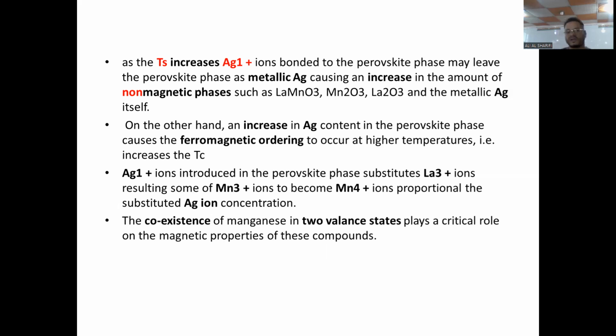Why, when increasing the sintering temperature, does the Curie temperature decrease and get far away from room temperature? Because the silver ions, or doping element ions, here it's silver, bonded to the perovskite phase may leave, may run away from the perovskite phase as metallic silver, causing an increase in the amount of non-magnetic phase. On the other hand, an increase in Ag content in the perovskite phase causes the ferromagnetic order. That means increasing the doping ratio is an advantage, an active thing to make the ferromagnetic ordering stronger and stronger at high temperature.